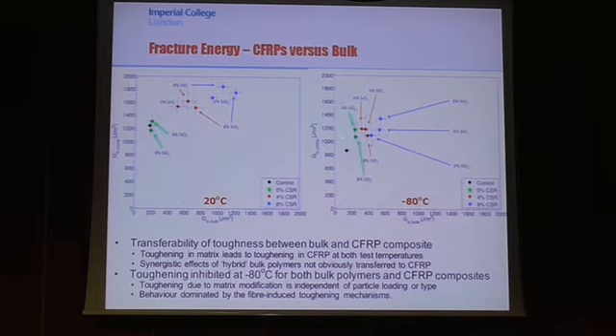And then at room temperature as well, or at minus 80 degrees, we can see that as we add in the silica and the CSRs, we get an increase in toughness of the composites, but we don't really see any kind of actual trend, because the error bars of the carbon fibre are masking basically what's happening with the matrix.